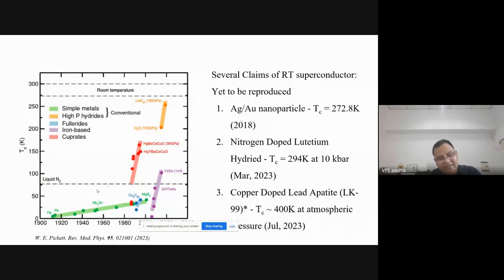And if you apply pressure, like iron selenide in 1 unit cell and all that, on the textured thin films, you can get even up to above 100 Kelvin TC. In fact, that superconductivity is also not yet explained on the BCS basis. So these were two exotic things which happened, one in 1986, another around 2006.